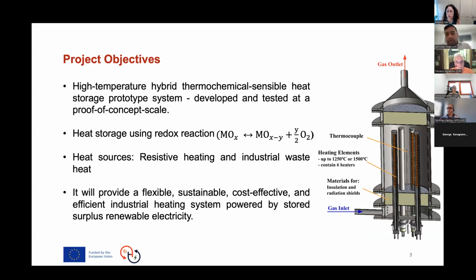Now, from the chemical reaction side, we are using metal oxides as the reactive material. You can see here the reaction. It's very straightforward. You have metal oxide, you provide heat, and because of this heat, at some point you release oxygen, and you reduce high valence metal oxide to a lower valence metal oxide, which still stays in the solid form. Oxygen is a gas, you take it out. You can reverse the process, and by doing so, you can recover the heat you stored in. It's the delta H, the enthalpy change of your reaction.